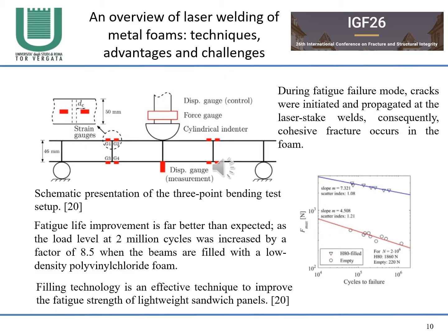In this picture, a schematic presentation of the three-point bending test setup is reported. During fatigue failure mode, cracks were initiated and propagated at the laser-stake welds. Consequently, cohesive fracture occurs in the foam.